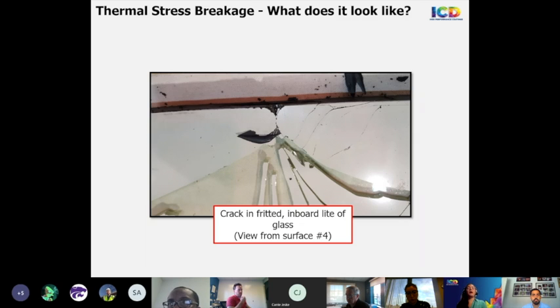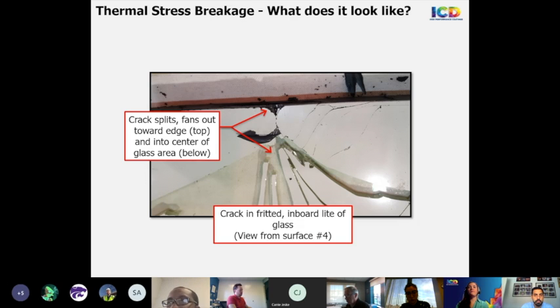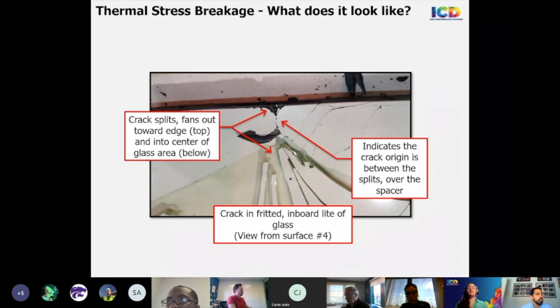So taking that unit out and flipping it around, now we are looking at surface number 4, which is referring to the interior facing surface with an applied ceramic frit. The crack is on top and moves downward toward where it fans out to the center of glass area, and the crack progresses toward the edge of the glass, fanning outward in that direction as well. And this tells us that the crack origin is somewhere in this region between the two fans, which is significant because cracks in annealed glass typically begin right at the edge of the glass. And in this case, the crack is clearly beginning inward away from the edge.